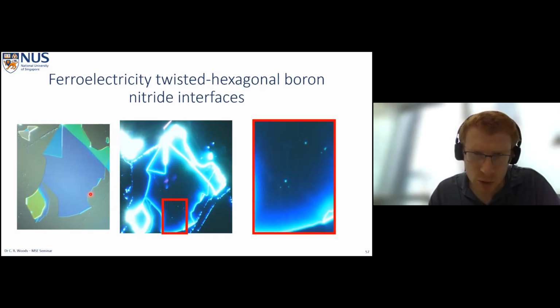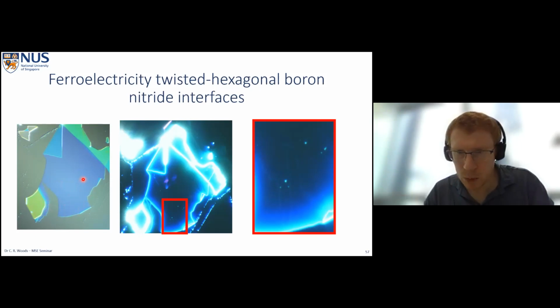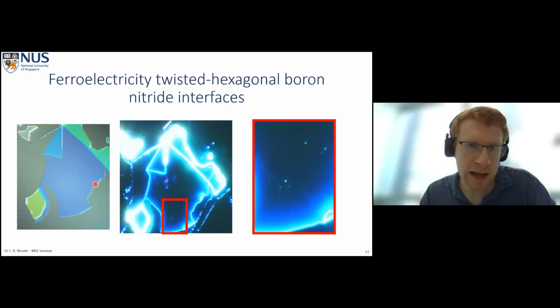And the same is true for pretty much all van der Waals 2D crystals. And so what you can do is you have these straight edges. You can take a straight edge in this crystal and a straight edge in the crystal that you put on top. So you have two hexagonal boron nitrides, you bring them together, but they both have this very straight edge, and you align these straight edges together. Because you know that they will be zigzag or armchair directions, we know that we'll have almost perfect crystallographic